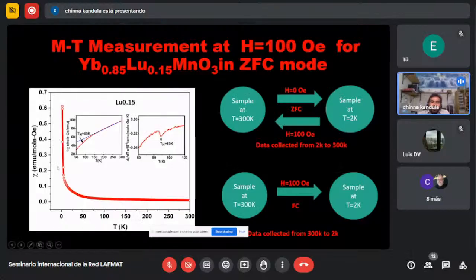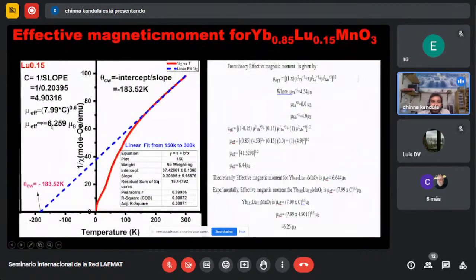In order to know what nature it takes on from room temperature down to lower temperature, you have to take 1 over chi versus T. It gives a better understanding of whether it follows antiferromagnetic or paramagnetic nature. So for that, I take 1 over chi. Here is chi versus T, and in the next slide it shows 1 over chi versus T. Here it shows linear behavior, because the Curie-Weiss law shows a linear part.